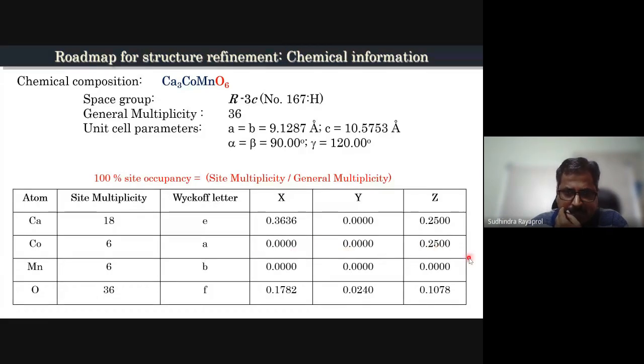This is a special position, so there is no possibility for me to refine this one. Okay. Similarly, manganese is at the 6b position. Again, this is 0,0,0, which is actually the origin of the unit cell. Okay. Now oxygen is 36f, which is basically a general site. So I have x, y, and z positions. Again, the values of x, y, z have to come from the crystallographic information about this sample. Either I have to refine it or I have to fix that. Use the literature value to start with.